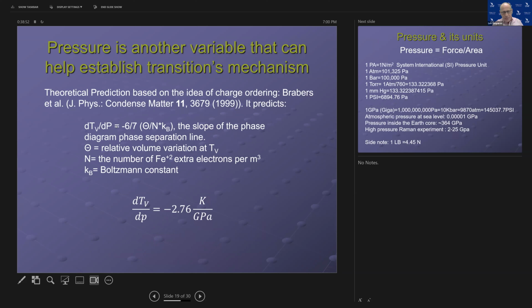All those parameters can be calculated or measured, and this parameter, the slope of the line, can be measured if you know the phase diagram. So to test this experimentally, and I'm an experimentalist, what I would like to do is find how the transition temperature changes with pressure, and then see whether the slope of that phase diagram separation line is similar to what's predicted by the theory. That's very often what happens with science. You have a theory, but then you have an experiment that either disproves the theory or confirms it. So that's the classical scientific method.